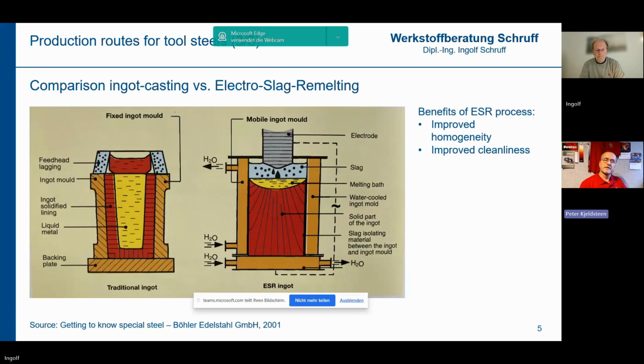And can you add more electrodes, make it almost continuous? Are they welded together or are they just stacked? It depends on the equipment that you have. In some cases, you have a so-called sliding mold. That means the mold itself is stationary, but the newly solidified ingot, the ESR material, is moving down. And you can continue feeding from the top by inserting a new electrode.